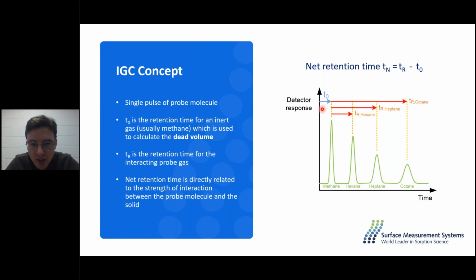Now, everything that we get as regards retention times from our interacting probes now has this dead volume taken away from it. So now what we get is this value of net retention time. And it is this net retention time that directly relates to the strength of interaction between the probe molecule, such as hexane, heptane, and octane. That net retention time is directly related to the strength of that interaction between the probe and the solid.